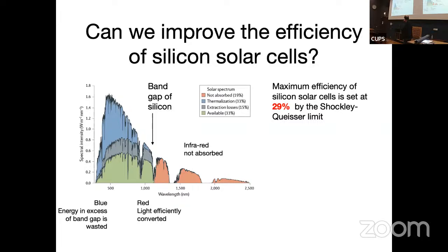any single junction semiconductor photovoltaic is that how well it works is given by its band gap. So the band gap of silicon corresponds to a little bit more than 1,000 nanometers. Silicon is transparent in the infrared, so any infrared light that comes in is not absorbed by a silicon solar cell. But it's not much better on the blue side, because actually